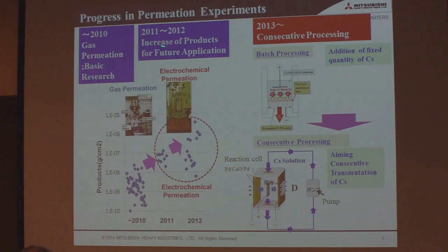And after that, from 2011, 2012, we focused on the increase of products for future application. And we used electrochemical permeation. Using electrochemical permeation, we can get more products, about 2 or 3 orders larger than the gas permeation method. And then, recently, we are aiming at consecutive processing.